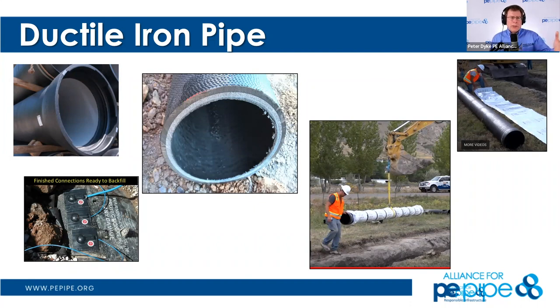So what have the ductile iron people done to keep their product relevant? Well, they coat the inside of it with cement. They wrap the outside of it with polyethylene. And then they connect it up to electric mechanisms for anodes and cathodes so that stray currents don't damage it. How much do you have to do to their pipe where it's not their pipe anymore? So polyethylene-wrapped ductile iron is what you're buying today. Bellevue, Washington, well-run system, 125-year cycle time, just had that AC water main break. They love cement-lined, polyethylene-wrapped ductile iron. Are you kidding me? No wonder it's six times as expensive as polyethylene. Go ahead to the next slide.